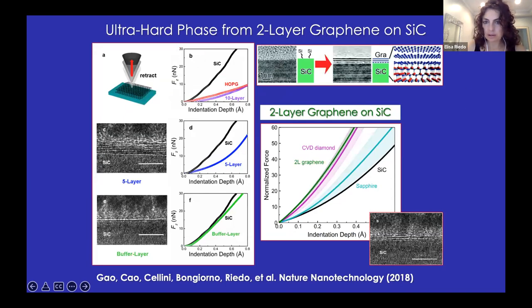So this is a typical image of epitaxial graphene. You have silicon carbide, then you have a buffer layer, and then you have one or two layers on top. Our results have indicated that by doing these indentation curves on bare silicon carbide, we get a Young modulus of about 400 gigapascal, which is what we expect for silicon carbide. On the other hand, for graphite, we get a transverse modulus of 36 gigapascal, which is exactly the transverse elastic modulus of graphite, which is the same as 10-layer graphene on silicon carbide.